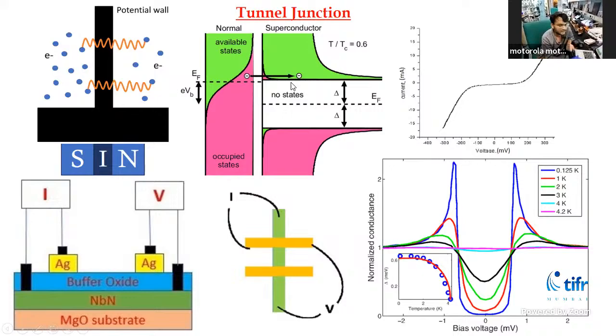But when we increase that voltage, that means we are giving more energy to our electrons, then there is a state from this region to this region, or this region to this region. The resistance comes into the picture, and with increasing voltage, the current will increase. If we differentiate these IV characteristics numerically with respect to V, we get this kind of conductance plot. We can see that between some particular value and another, there is zero conductance. That means there are no states available, as I showed you from the theoretical curves. So in this way, we can visualize the superconducting density of states in a superconductor.